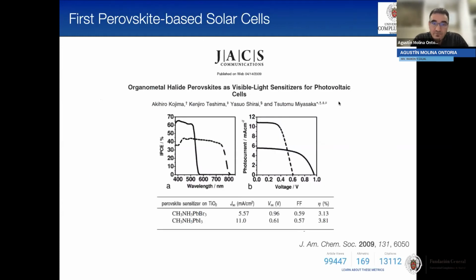Well, this is the first paper that was published in this field. It was published in 2009 by the group of Professor Miyasaka. And they used the approach of dye-sensitized solar cells. They used titanium oxide, they infiltrated the perovskite in this titanium oxide, and they used later on the redox pair of iodine, triiodine, liquid electrolyte.